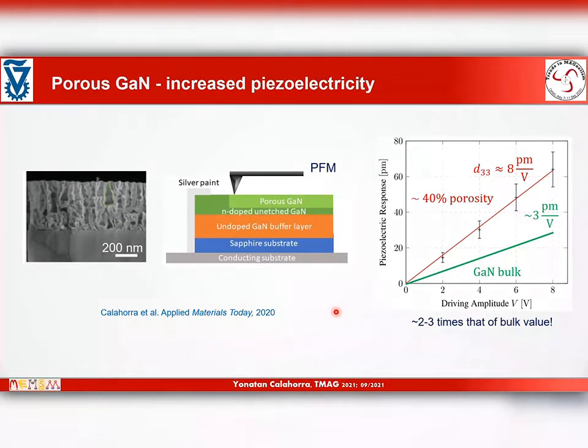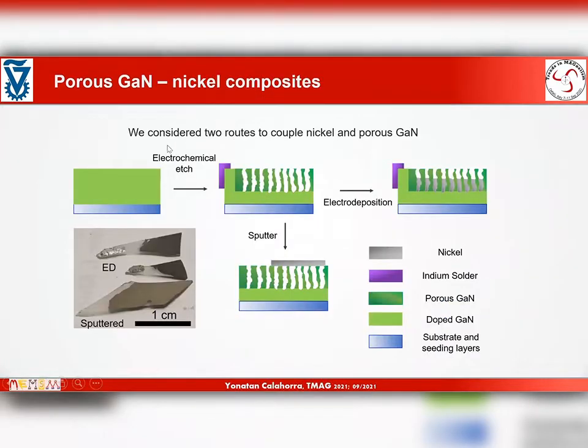So that's very inspiring in terms of piezoelectricity in itself, but we also thought it might be interesting to make a composite material, to fill these pores with something, and that something can be a magnetic material. So we have this process of electrochemically etching the gallium nitride to make it porous. And then we consider 2 routes to create the composites. One is to electrodeposit nickel inside the pores, or hopefully inside the pores, and the other is to sputter nickel directly on top of that layer.